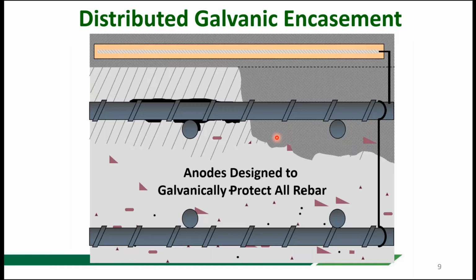Now, in terms of a galvanic encasement, we're doing very much the same thing, except that we're doing it on a distributed or a kind of a global, or at least an area basis. So instead of just having a single anode to protect a very localized area, we have a distributed anode that might be applied over the whole structure or section of the structure. And that anode is passing current to the steel, even in the areas where you have salt contaminated concrete remaining. That steel is protected and will either stop corroding or corrode at an insignificantly slow rate in the future. So that's the concept behind a galvanic encasement.